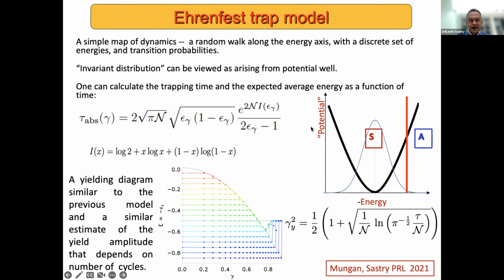So that becomes more clear by this further simplification of the description I make of the dynamics. If I didn't have this trapping feature in my dynamics, I imagine that I have some invariant distribution that I can think of as being a result of a confining potential. But in addition, I have a certain value of the energy of my state at which I get absorbed, because the energies beyond that red line that I've shown correspond to states which are stable under the deformation that I'm applying.